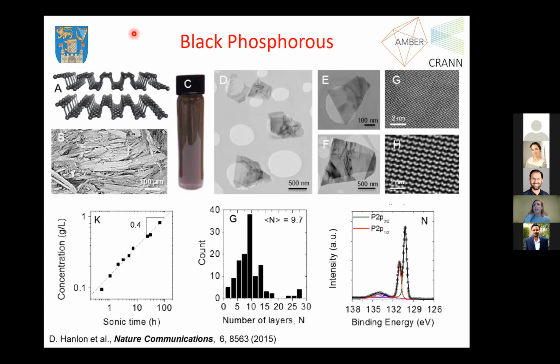What we discovered a few years ago was that we could use the same liquid phase exfoliation methodology to pick and choose compatible solvents. And these solvents had the overall result, again, of exfoliating it successfully. Here you can see some high resolution TEM work that shows the atomic resolution, and that it's pristine. There are no defects, and it's structurally pristine. What we showed was that the exfoliation was quite successful.